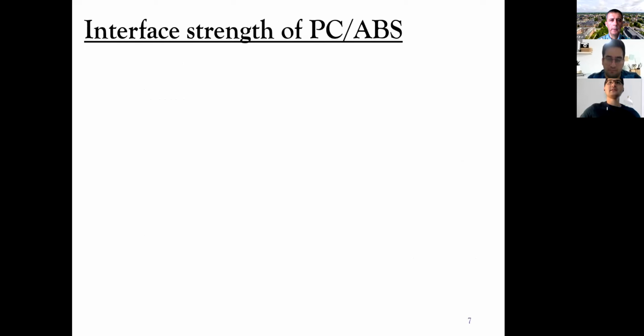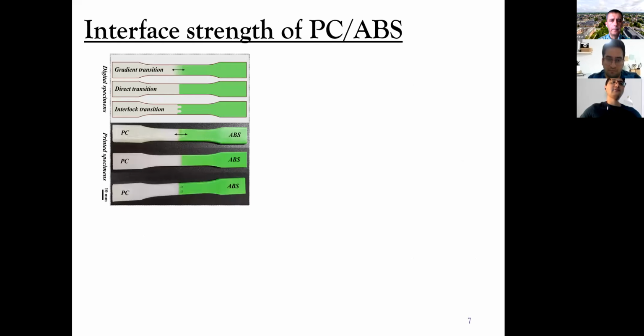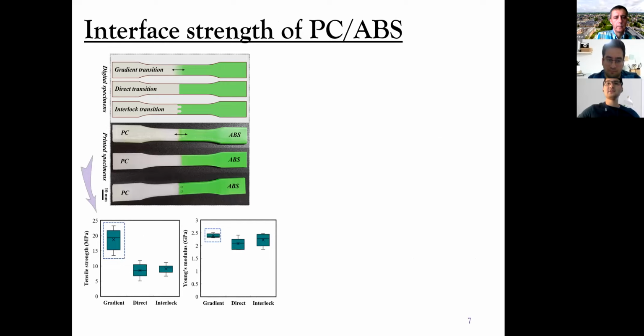Okay, let's take a look at interface strengths. We designed 3 different interface transition patterns to test using the tensile testing method. According to the results, the gradient transition materials showed higher tensile strength and stiffness than the direct and interlock mechanisms. We added interlock as well because we wanted to check how interlocking would help to increase the strength and stiffness of the conventional multi-material printed parts.